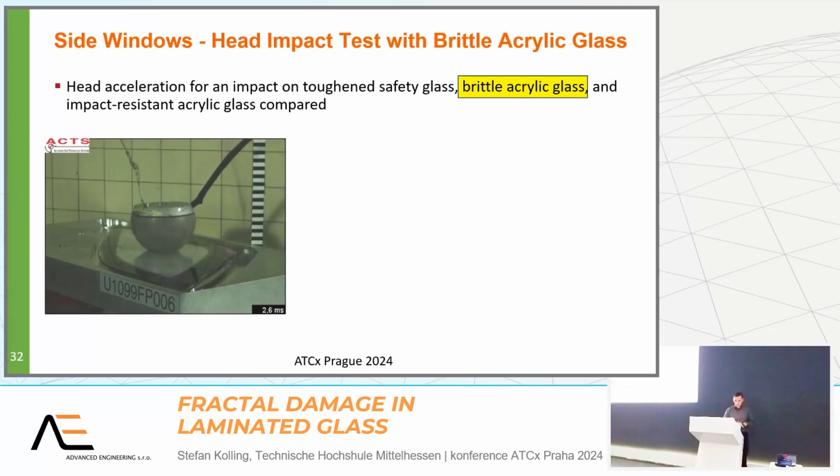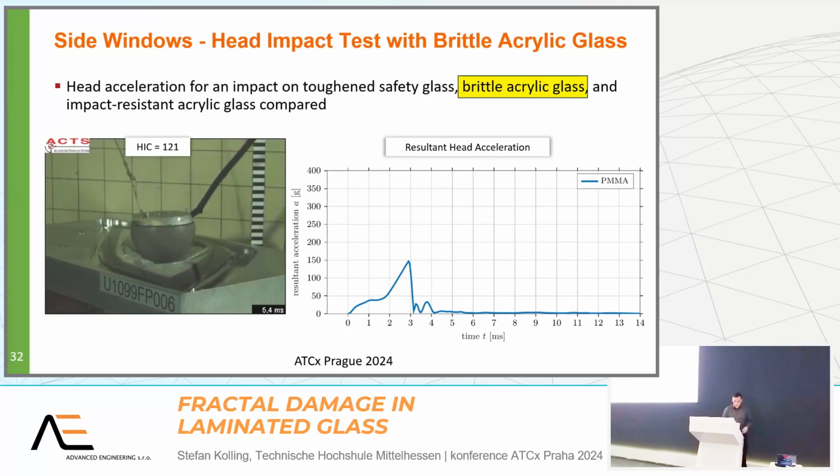Here is a brittle acrylic glass, and this is the acceleration. With 150 G, it is not critical. So PMMA can be used for that.